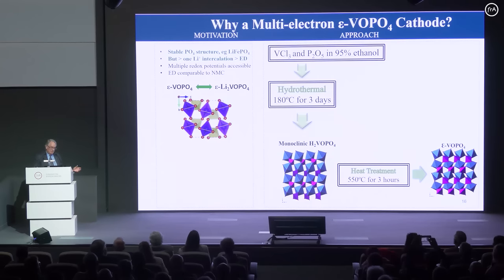So I mentioned the iron phosphates as being a material of particular interest. No nickel, no cobalt, very low cost, but it's also low energy density. To increase the energy density, we've got to get more lithium in. So we've been looking at materials based on vanadium. For the chemists in the audience, that means you can go from vanadium 5 to vanadium 4, then vanadium 3. So our goal was, can you in fact get two lithiums into a lattice? And is that lattice still stable after you've done that, or have you wrecked the lattice?